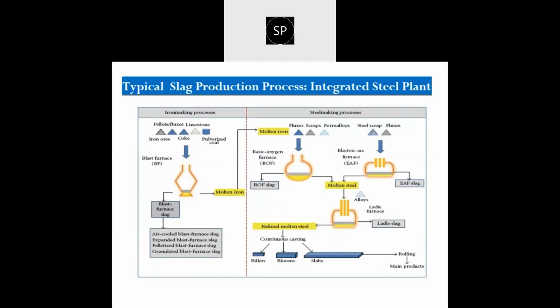During this process, once again, all these impurities accumulate on top of the molten iron in the form of a slag, and it is tapped from the furnace in molten form at 1500 to 1600 degrees centigrade temperature, and subsequently it is air cooled. Once it is air cooled, it becomes basic oxygen furnace steel slag, which is a good potential material for utilization as a substitute of natural aggregate in road construction.